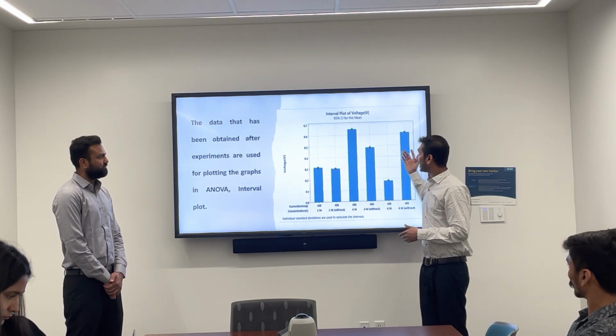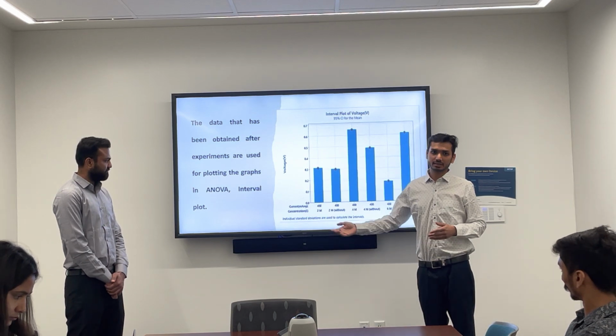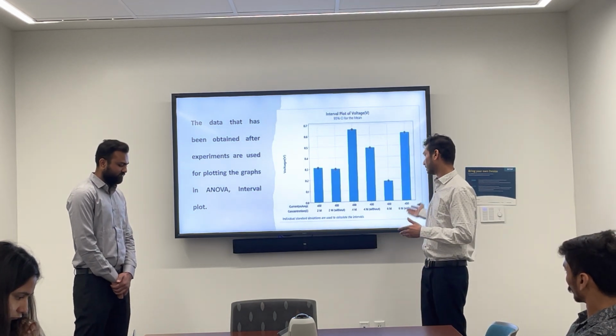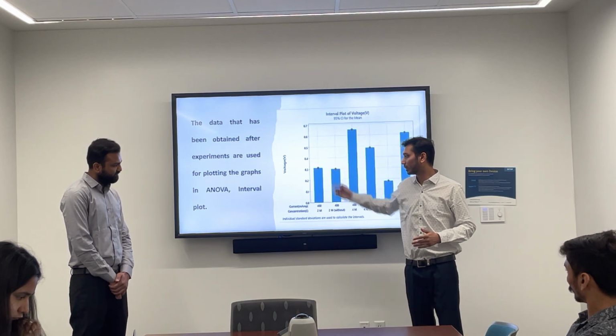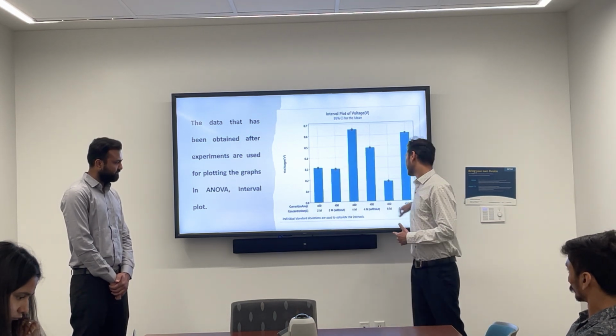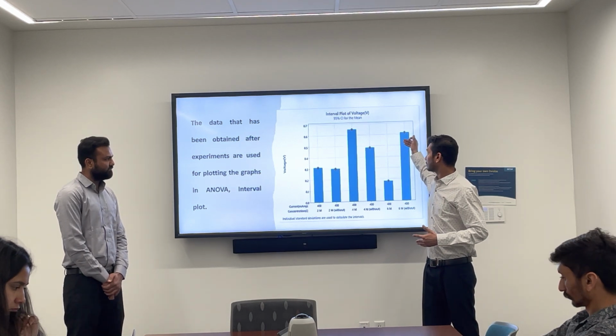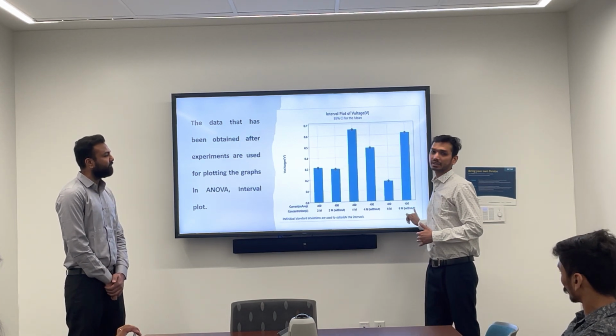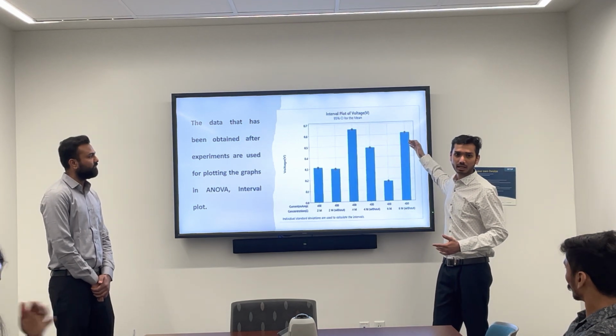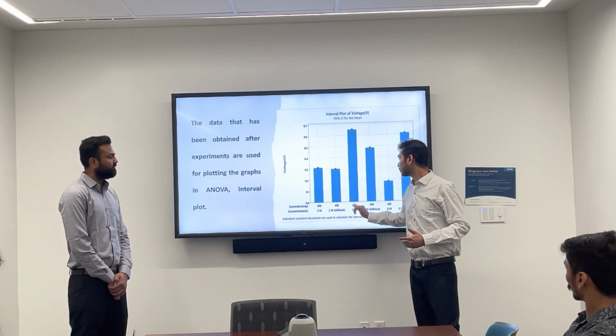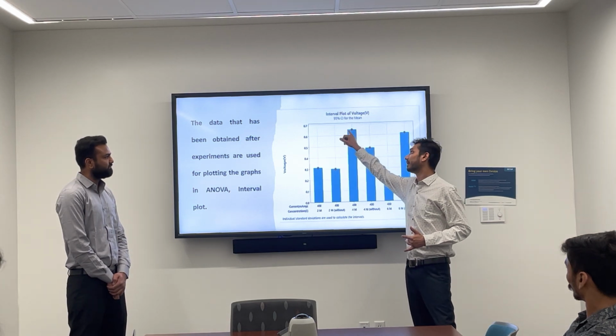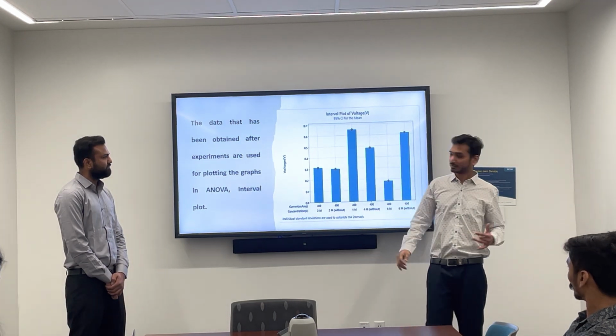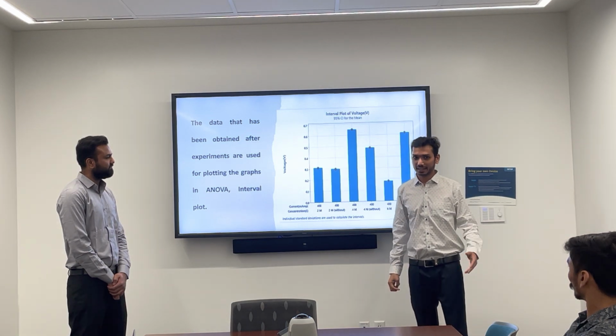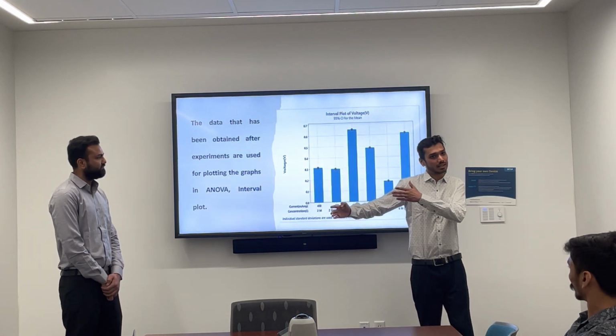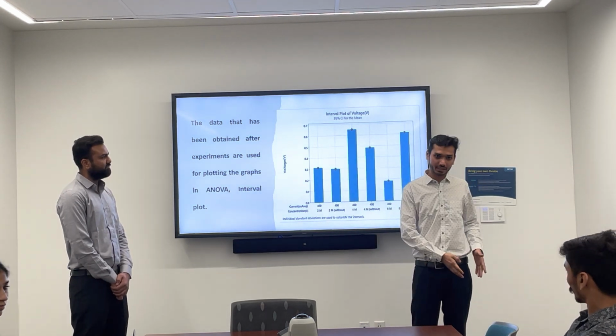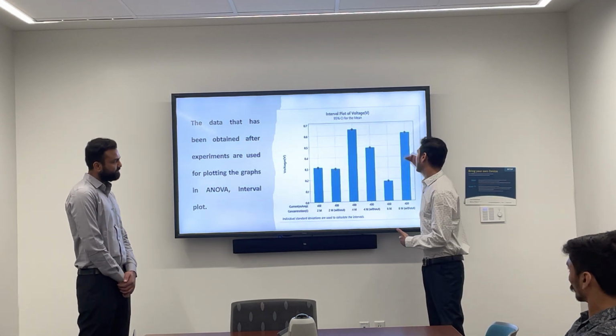And you are clearly seeing that increasing the concentration increases our power as well, because this data compares voltage and current against the concentration. So this interval plot shows that the 6 molar electrolyte solution gets more power. Actually it's better than the 4 molar as well, but as I'm saying, aluminum is self-reactive. So in the 6 molar, the battery lifespan will be decreased, but it gives more power.